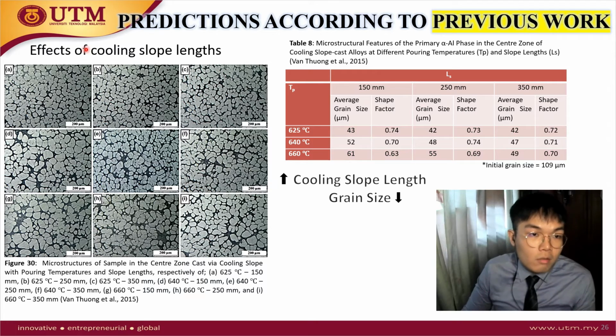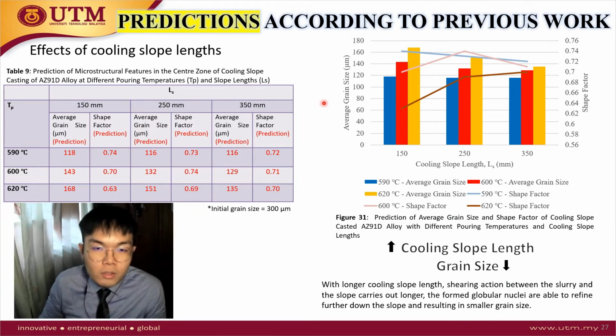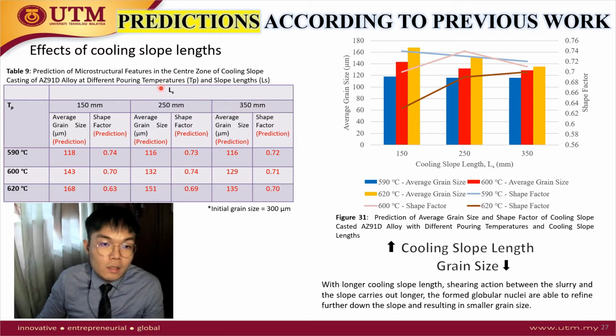And we move on to the effect of cooling slope length. From these images quantified in this table, we find that a longer cooling slope length results in a smaller grain size. To predict cooling slope casting of AZ91D magnesium alloy, we use the same slope lengths and our pouring temperature, and apply a similar percentage of reduction in grain size. The result is presented graphically in figure 31. With longer cooling slope length, we have smaller grain size. You can see the trend going lower.